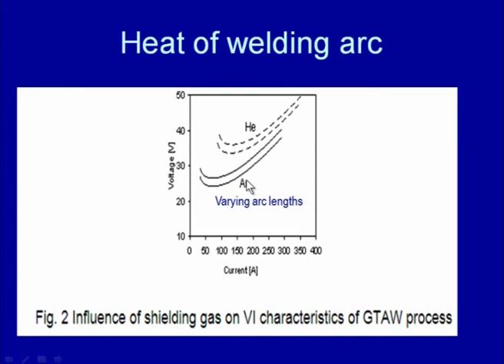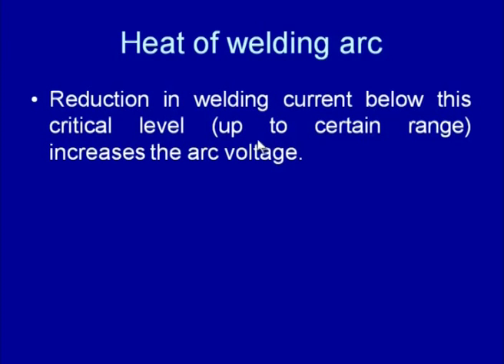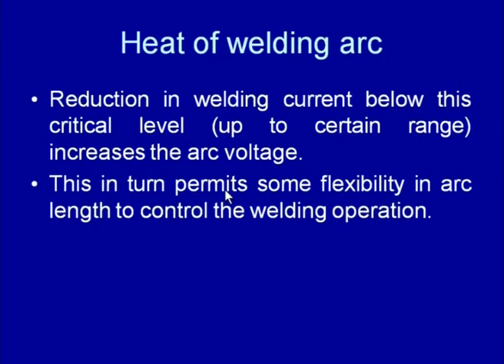And because of this, the minimum arc voltage is found at around 50 amperes for argon, while it is found around 100 to 150 amperes in case of helium. So, the reduction in welding current below this critical level, up to a certain stage, increases the arc voltage, and this in turn permits some flexibility in arc length control during welding.